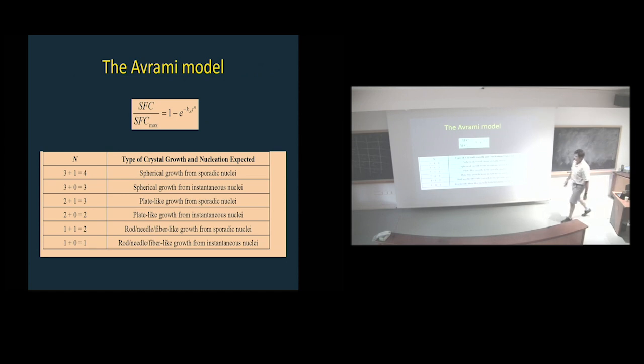And the nice thing is that you can maybe imagine that if you have a coefficient of 1, it is a needle-like growth from instantaneous nuclei. They appear like this. Sporadic is like in time. So this changes if you have a one-dimensional structure, some two-dimensional surface, or some ball. One-dimensional, two-dimensional, three-dimensional, and it's affected by the nucleation. Instantaneous, sporadic. And you can look at it, right? If you have different sizes, it was sporadic, right? If all the crystals are the same sizes, probably was instantaneous. And then, of course, this never happens. You get 2.3 or something like that.